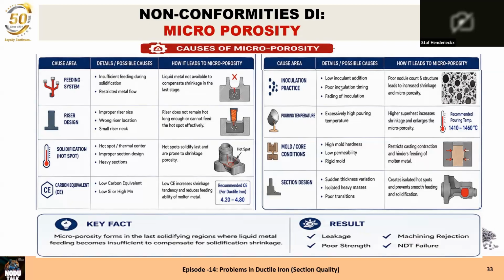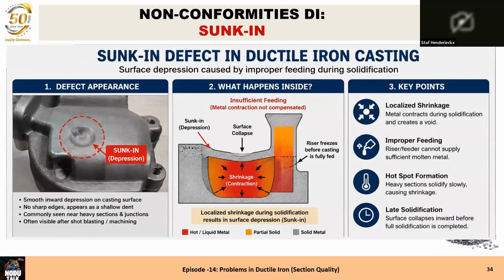Again, the key fact is it's formed in the last solidifying metal area, and the feeding was insufficient. So it's in between risers. It's under a riser when the riser neck is solidifying too early, and it can be in hot spot sections, but then it's not that big, because in a hot section it starts with micro and goes over to macro. What's the problem? Leakage, of course, poor strength, machining rejection, and problems with the NDT testing. So, sunk in: many times foundries and even customers don't see it when it's small, but when it's big, you really will see it.